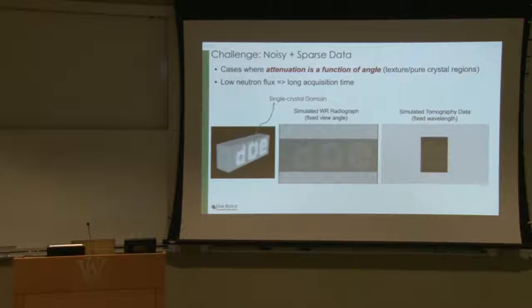The second thing is that you may have a low neutron flux. So unlike in X-ray tomography, neutron acquisition can take a long time. It's a pretty niche application. So it can take probably an hour to get one hyperspectral image. I'm just making a number up, it all depends on the sample. But if you want to acquire 50 angles, that's 50 hours of experiment time. And the flux tends to be pretty bad.